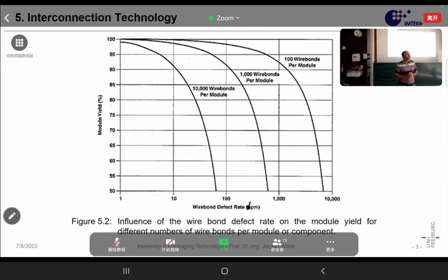And so let's say 10,000 DPM. That doesn't sound so bad, because you do 100 wire bonds and one is not okay. So doing that in the lab for your master thesis, I would say you're not so bad. But now with such a yield, here 10,000 DPM is a yield per bond of 99%. You must keep that in mind. Here that would be a yield of 99.9%.